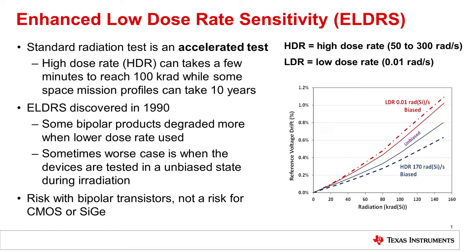It was discovered that some bipolar products degrade more at low dose rate than they do at high dose rate, and sometimes the worst case is when devices are tested in a non-biased state instead of being biased — aka powered up. So in response, the industry defined a new test term, ELDRS, for enhanced low dose rate sensitivity.